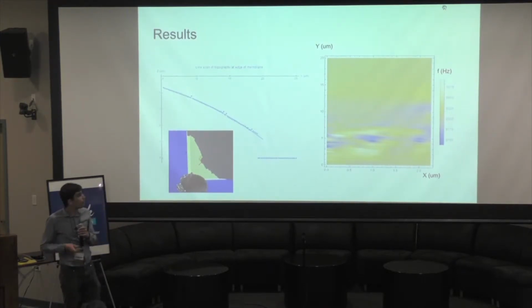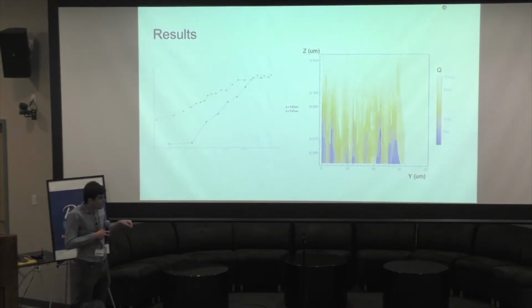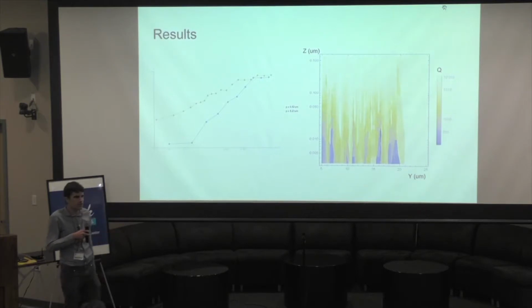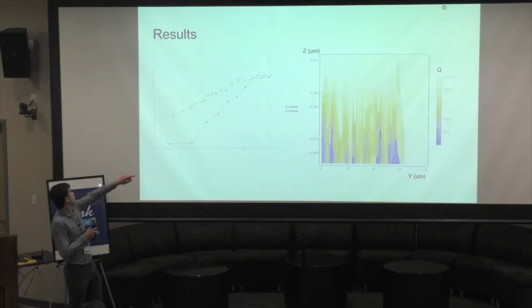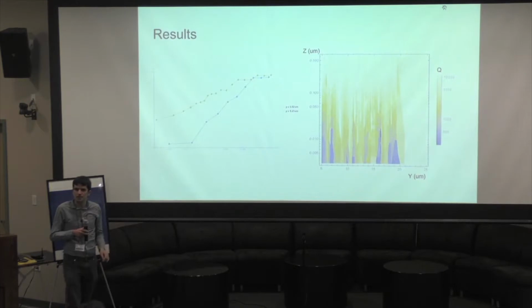The more interesting measurements that we did, though, were, again along the same line scan, measuring the dissipation as a function of cantilever-sample standoff. You can see a couple of sample dissipation curves on the left. We are able to get much finer resolution data at the cost of spending more time, and for these scanning measurements, it already takes a few minutes per point.